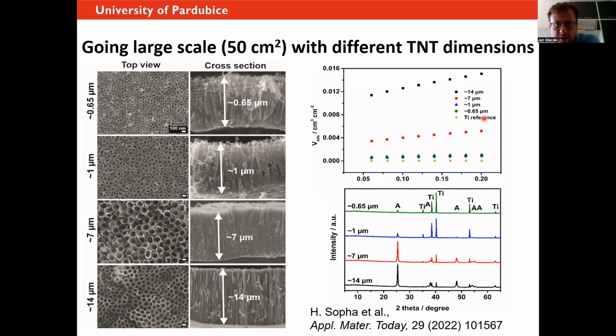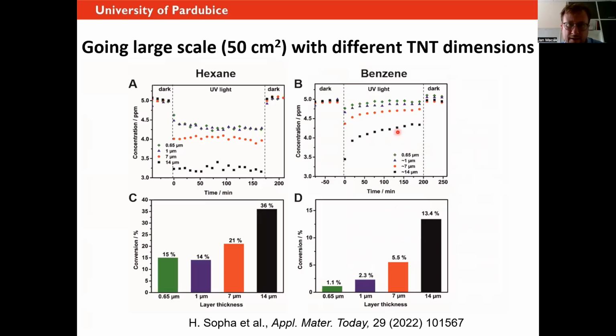And we were actually doing also for the first time some extensive texture analysis, because the amount of tubes is now sufficient to do some texture analysis by the BET. So we can get some pore volume and so on. And here is the result, probably somehow not surprising. And it says that for hexane and benzene, the thicker the layers, the higher is the decomposition. And we haven't reached, for the thickest layer we used, saturation yet.